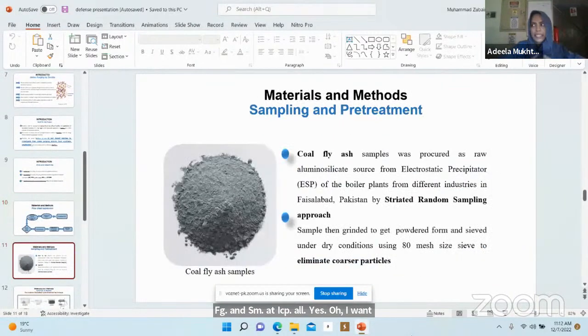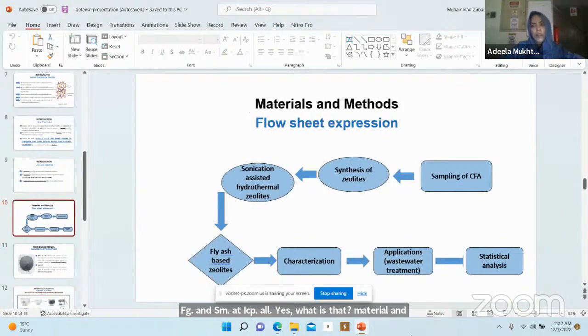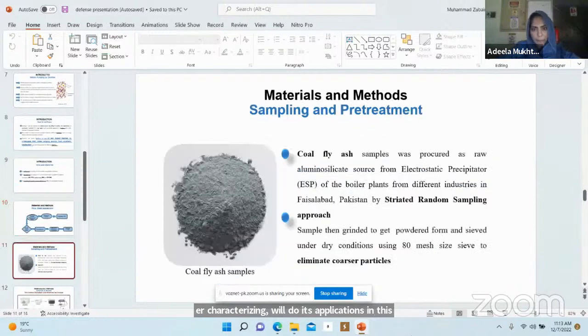What are the material and methodology to synthesize zeolites from coal fly ash? First of all, we'll do sampling of coal fly ash, then synthesize zeolites from coal fly ash through a sonication-assisted synthesis technique and a conventional hydrothermal technique. By this, we'll synthesize fly ash-based zeolites. We'll characterize them using FTIR, SEM, and ICP-OES. And then after characterizing, we'll do their applications in wastewater treatment, then statistical analysis. Materials and methods. The second point is sampling and pre-treatment. We'll collect coal fly ash, a raw aluminosilicate source, from the electrostatic precipitator of the boiler plants in different industries of Faisalabad.